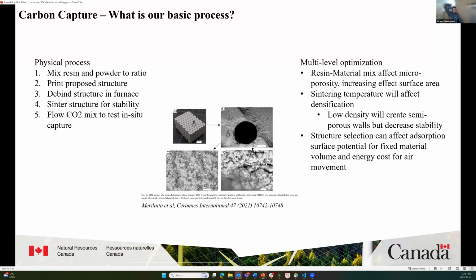So we defined a simple basic process, and we learned some things even just from doing some manual testing. If you mix the resin and powder, we realized you have control of how much powder you mix with the resin. We can vary it and still be printable and self-sustaining in a range of about 20% powder up to, I think it was 42% powder, at which point we stopped being able to print because it gets too viscous. We then print the proposed structure.